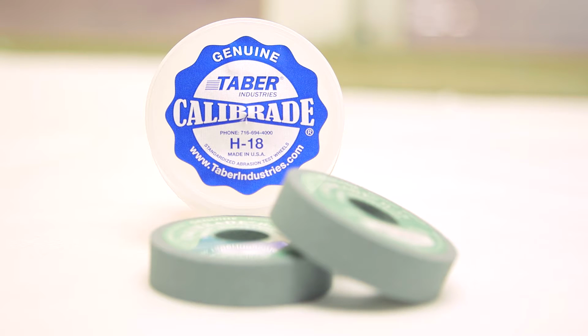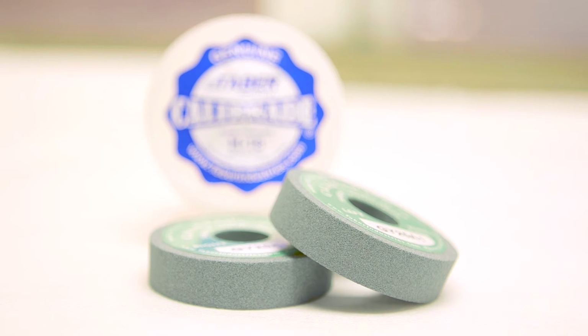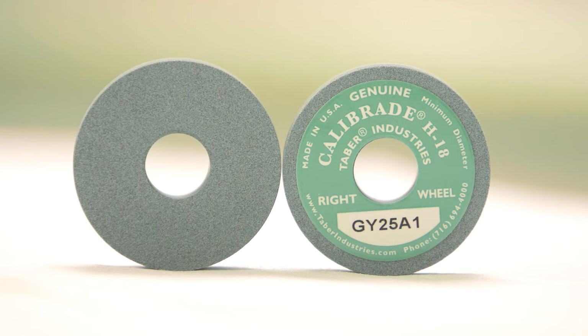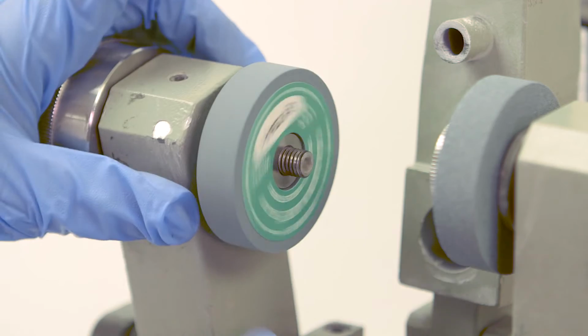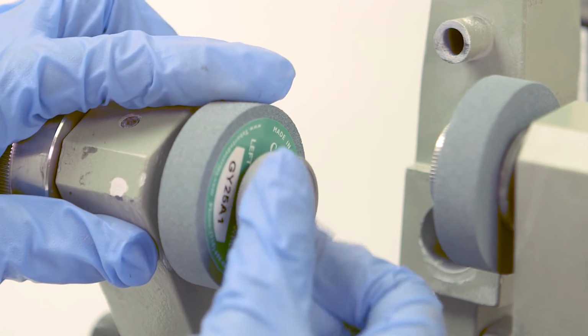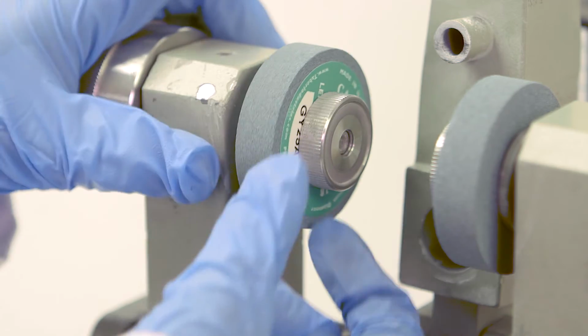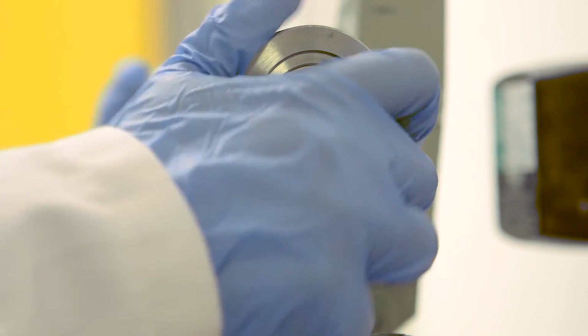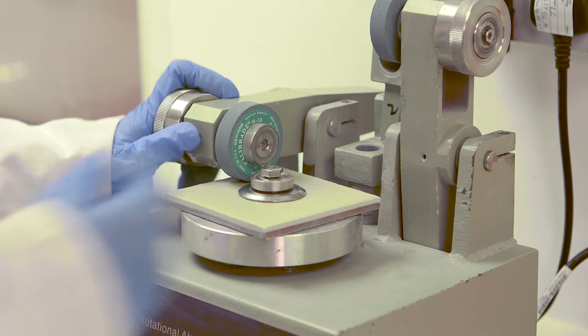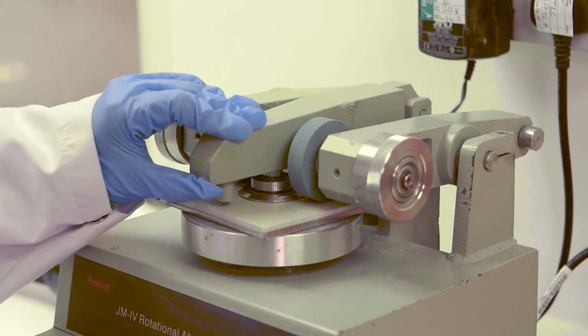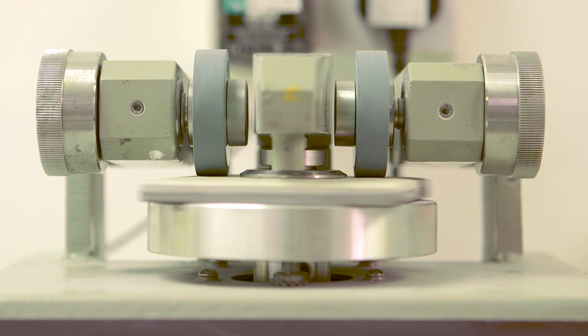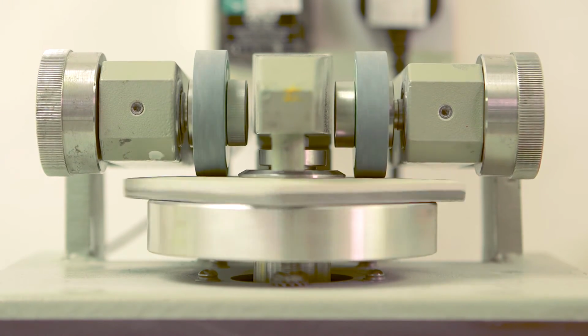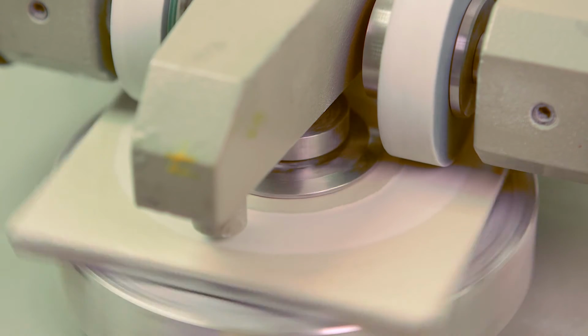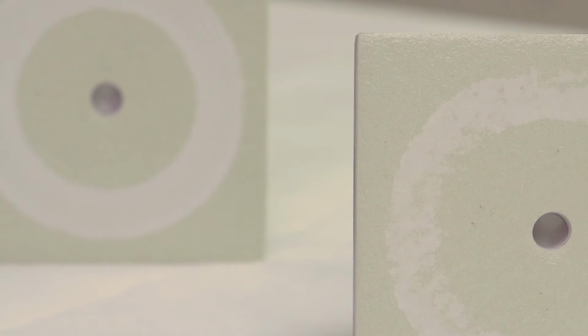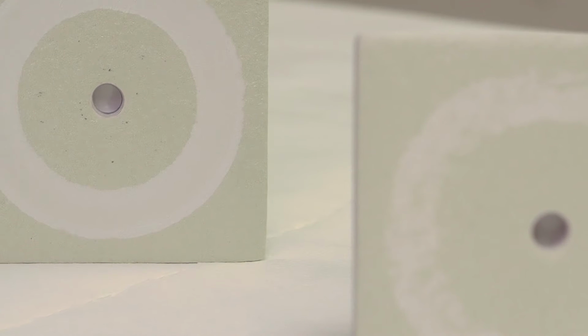The rotary abrader consists of a pair of wheels made from an abrasive compound, variable in grain size and hardness to suit the material being tested. The wheels are free to rotate and are mounted on an axle, offset to the center of the drive shaft rotation to cause a scuffing effect. The wheels are loaded with a weight, usually 1 kilo, to give them a downward force on the test plate. As the wheels rotate, they wear a groove in the test plate. After a certain number of revolutions, normally 1,000, the machine is stopped and the test plate measured to find the loss in weight caused by the abrasion in grams.